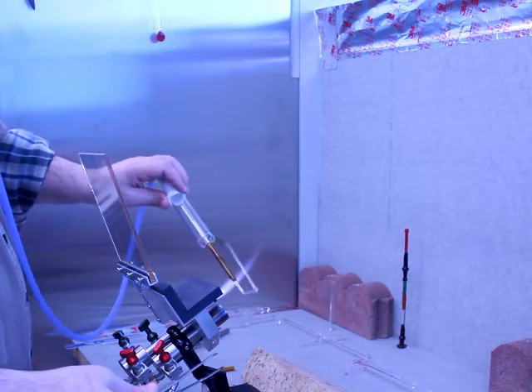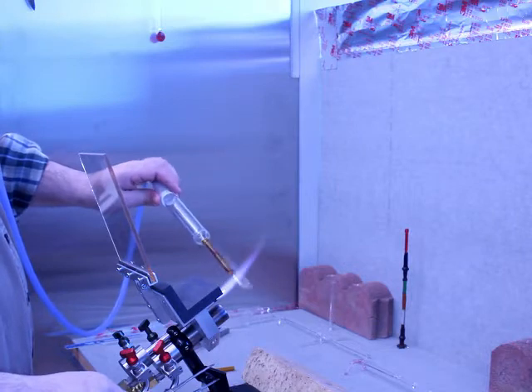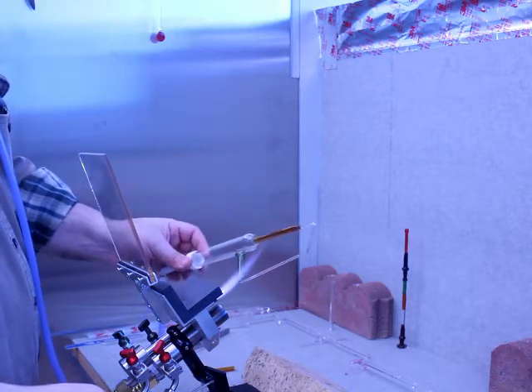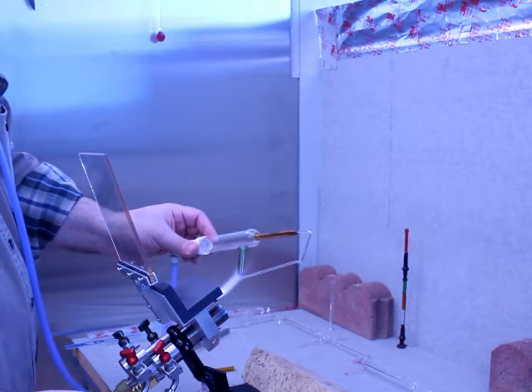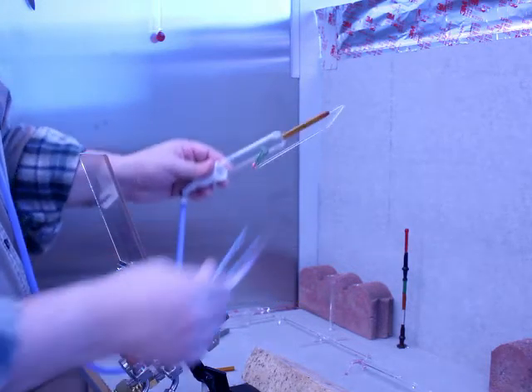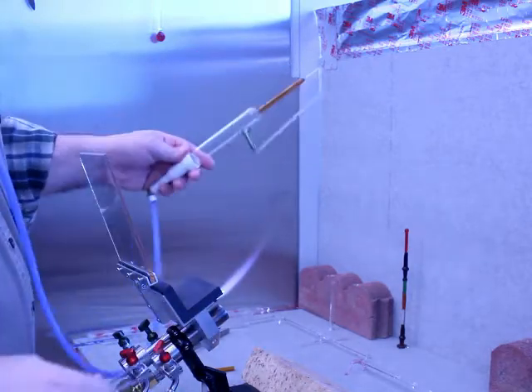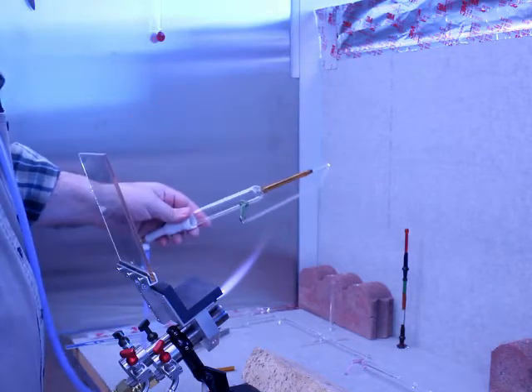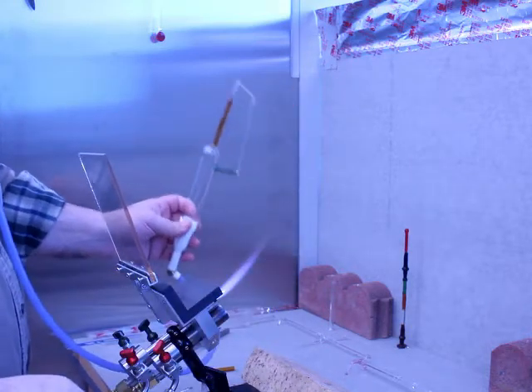I'm reheating all the points of the bridge just to make sure I don't have any significant amount of stress that's going to cause it to break in a moment. So I come back here, heat this. Okay, so now, even though I still need to do a lot of work on my ring seal and my straight seal, this bridge adds stability. So now I can take the hand torch and come in here and clean some stuff up.